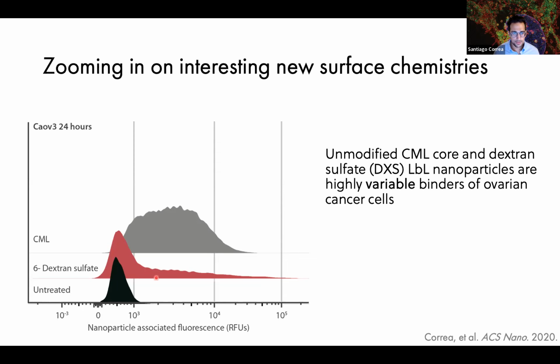While we do have some cells that have nanoparticles associated with them, the vast majority of cells are ignoring these nanoparticles. That's in pretty stark contrast to the gray data. This is our carboxy modified latex, that core material, so the core without any of the LBL film. We see a very broad distribution, a lot more cells taking up these nanoparticles, but we still see some cells that are not taking up the particle at all. And so both of these distributions are pretty different from what we're wanting to see.